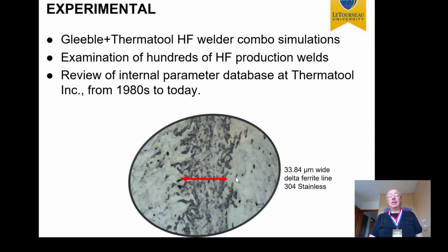So what we did was a work at LeTourneau University in which we experimentally combined a thermomechanical simulator called a Gleeble with a Thermatool welder, where I want to acknowledge the help and the support from Thermatool Corporation. They also gave us the opportunity to look at hundreds of production welds made on lines that have Thermatool high-frequency welders. And so this is a close-up of a bond line. You can see 33, 34 microns, so it's the same low order of magnitude of bond line, of ferrite in an austenitic steel.